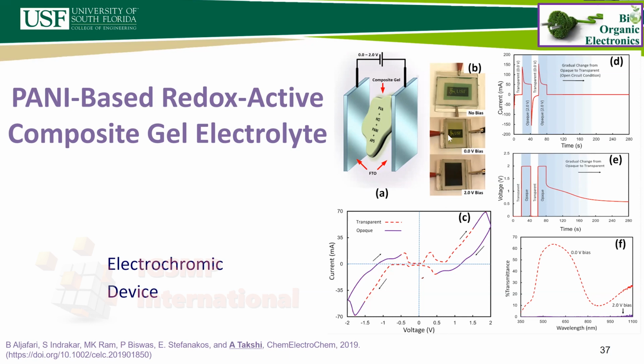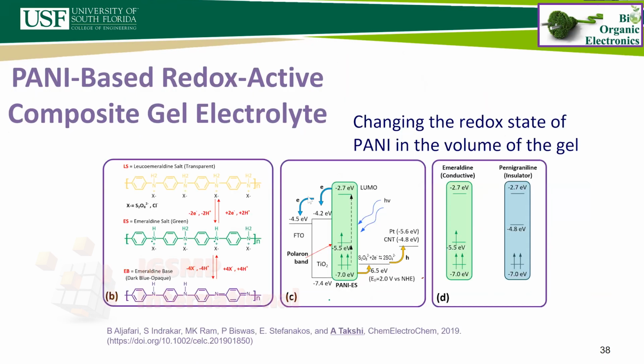But when you apply 0 volt, it becomes quite transparent, and you can sort of use it as electrochromic windows. But once we got to this part, we had to analyze what exactly is happening, how the redox state of the polymer changes inside the volume of the gel. We hypothesized that it is because of the ability of the gel for conducting both electronic and ionic charges at the same time, and the interaction between these two different types of charges can assess the change in the redox state of the conducting polymer.